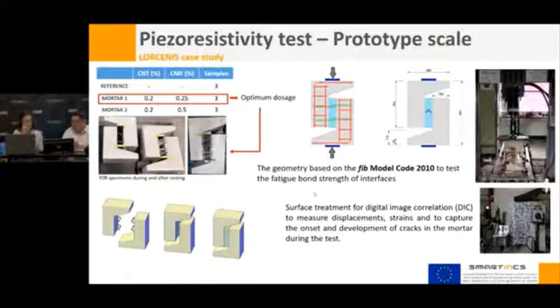For the mechanical characterization and the piezoresistivity test, we use digital image correlation to measure displacements and strains, and also to capture the onset and development of cracks in the mortar during the test. As you can see here, it is this one. The technique consists of taking several pictures during the test, and then with software you process those images to see the displacements and strains on the sample. You have to paint the section you want to study with a speckle pattern.